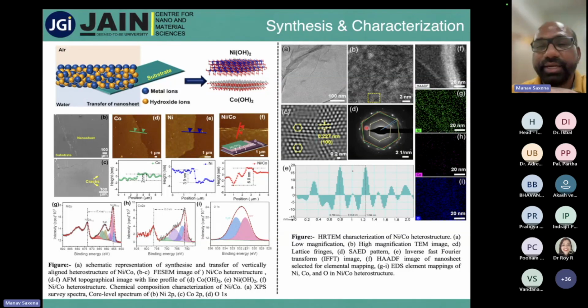And based on the SAD pattern we have shown, and also the d-spacing and the elemental mapping G, H, and I, it shows the whole distribution of the cobalt and nickel in the heterostructure. Here we are presenting the data where nickel is on the top and cobalt on the substrate.